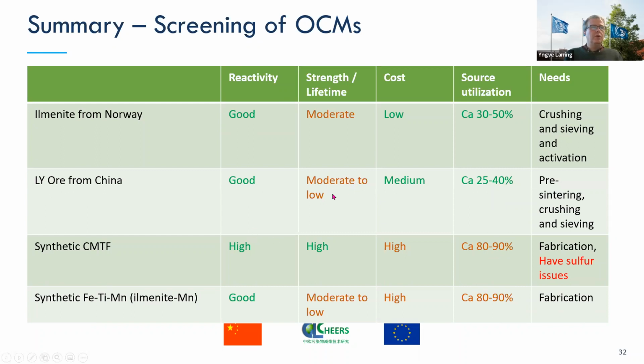The LY ore is also good, moderate to low strength, medium cost, and also synthetic here, high reactivity, high strength, but it's also high cost, or higher cost at least than the other one. And this last one as well, the synthetic one, because you need a fabrication part. But we should not forget that those ones need pre-sintering sometimes, crushing and sieving, which also make them not as cheap as one thinks often. But the ilmenite we buy with low cost is already sieved and crushed, which is a very big benefit for us. So therefore, the ilmenite was the one which was selected for the first generation, and this we can come back to also in the next presentation, where I did this even deeper selection of the materials.